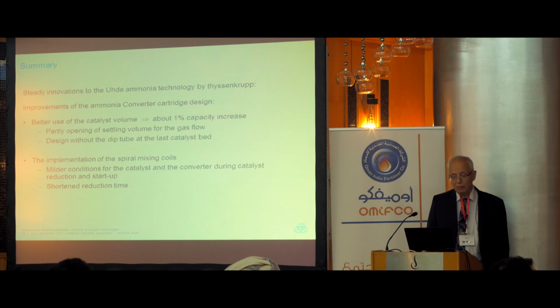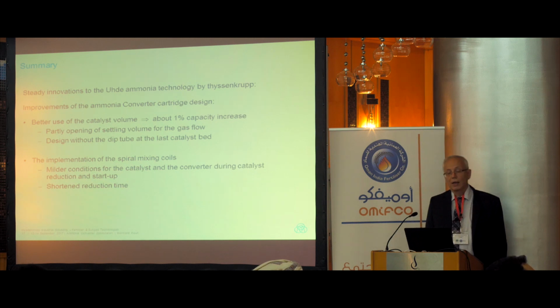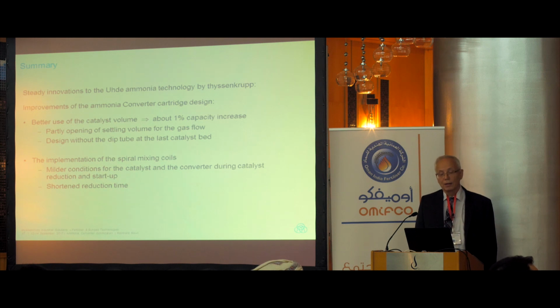So, coming already to the summary of my presentation. Steady innovations to our ammonia technology, especially in the ammonia synthesis area, will improve continuously the design of this unit. What we have seen today here is better use of the catalyst volume. About 1% capacity increase can be achieved by partly opening the settling volume to the gas flow into the converter bed, and the design without the dip tube also improves the ammonia converter performance.